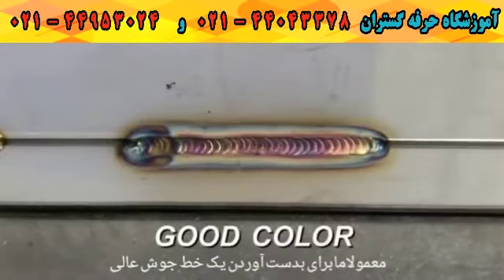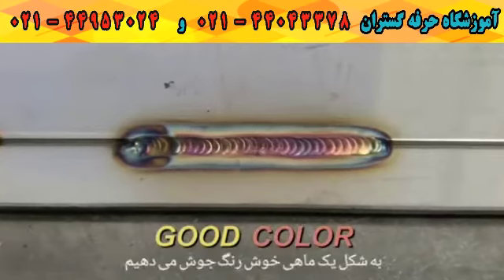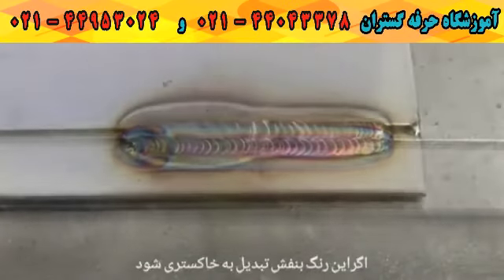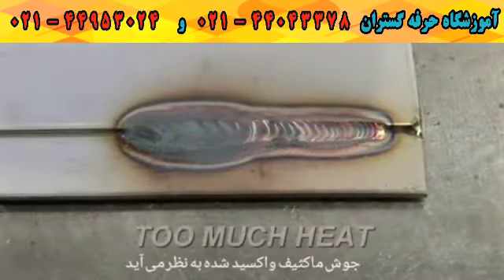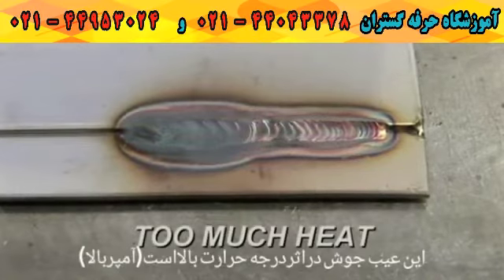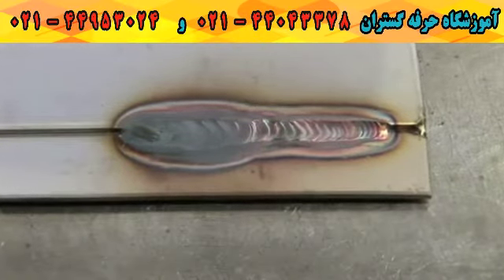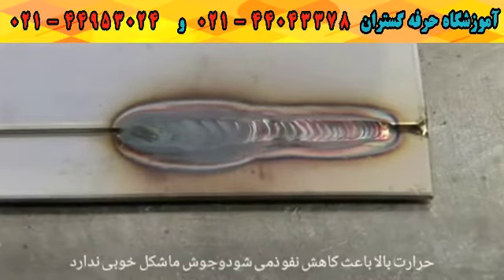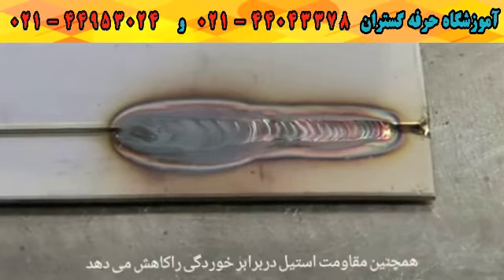When it comes to the weld appearance and warpage issues with stainless steel, it really boils down to one key problem. Too much heat is being applied. And a good indicator of this is the color change the weld area goes through. Typically we're shooting for a light straw to a nice salmon color. If you're getting those deep dark purples to a gray that looks dirty and heavily oxidized, that's too much heat. Not only does it not look good, but it also reduces the corrosion resistance of your stainless steel.